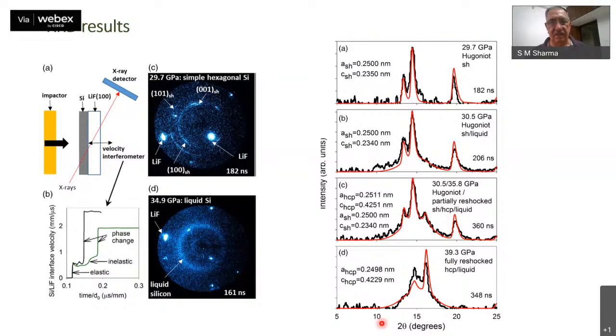Here are some of the one-dimensional curves which were deduced from here. Unlike simple X-ray diffraction experiments under static pressure, in shock compression one has to calculate back the profile because there are lots of other components in this, and the geometry is a little unusual. So we calculated the diffraction patterns and compared them with the observed ones. At somewhere close to 30 GPa, the pattern is essentially of the primitive hexagonal phase. At slightly higher pressure, you start seeing a little broadening.